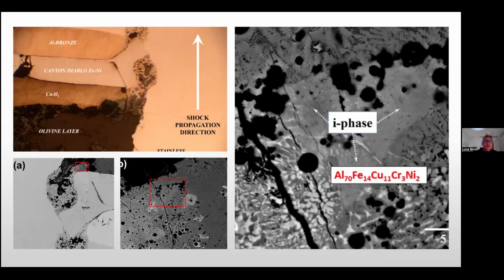You can see on the top left the experiment we designed with Paul. We decided to use not a single-layer sample, but a combination of different discs stuck together. We selected a disc of olivine with a composition close to that observed in the Khatyrka meteorite, a piece of copper-aluminum alloy, then a piece of natural Canyon Diablo iron-nickel alloy, and then a piece of commercial aluminum bronze. Everything was stuck together and hit by the metallic projectile, because the four discs are stuck together in the stainless steel chamber.